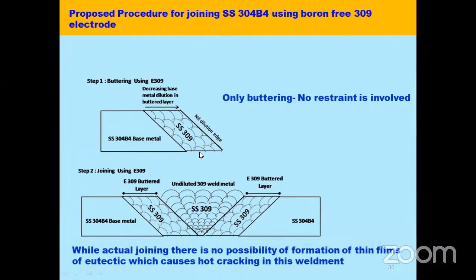We have already seen that hot cracking occurs only in the presence of low melting eutectic liquid in the fusion zone, as well as restraint, that is shrinkage stresses or any geometrically developed restraint in the structure. So here restraint is very low, so the probability of cracking is very low. We have to give a sufficient buildup such that the base metal dilution on the surface of the edge to be joined is almost zero.